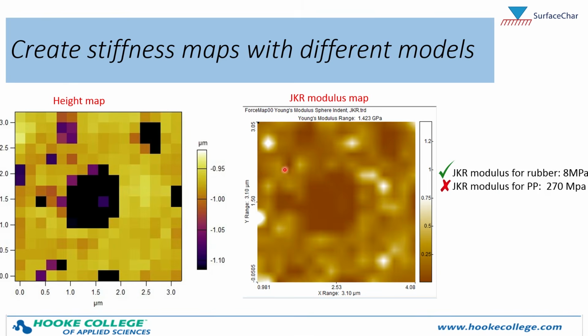Then we can create a stiffness map using the different models available to us. Again, I'm using as a reference our height map here on the left. What I did here was that I fit each force curve using the JKR model. And I picked the JKR model because I actually know it is the one that is appropriate for this rubber material here. By doing that, I can create a JKR modulus map now, where the Z range is in units of gigapascals.